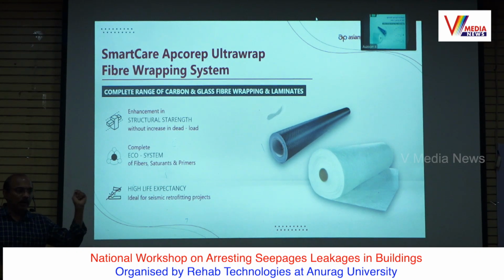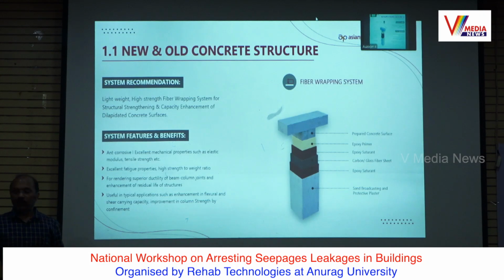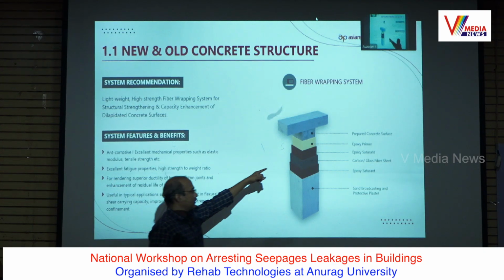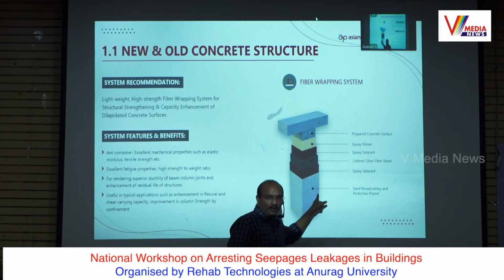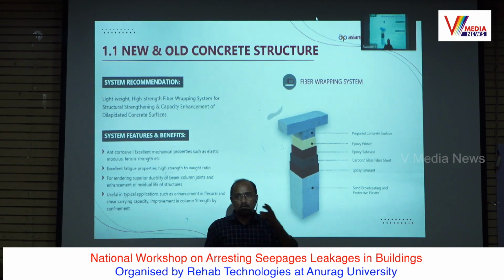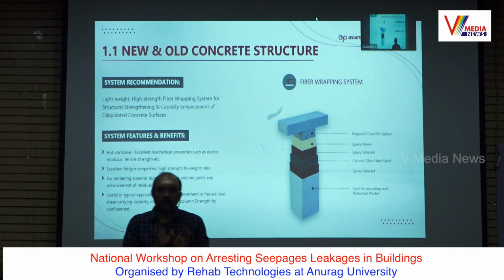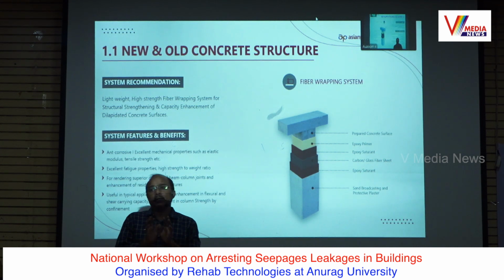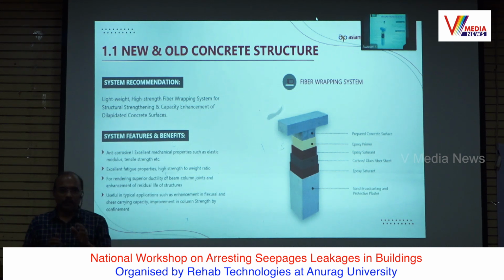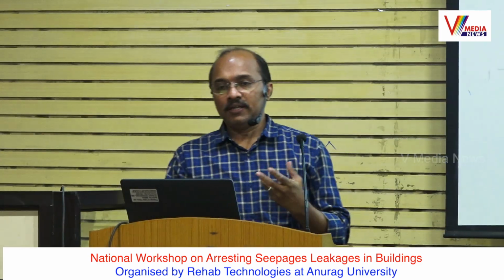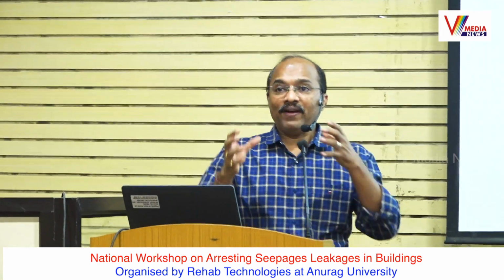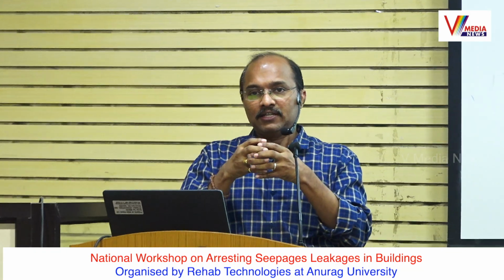So this is applied onto the concrete column or on a beam by putting epoxy adhesive. Subsequently, we also put one more layer of this epoxy saturant adhesive on top of it, and finally put some sand on top of it, and it is broadcasted, so that it is not exposed to the environment, and it gives you the required strength in that particular area. So you enhance the strength by confining the concrete and increasing its strength. This is called fibre wrapping structure.